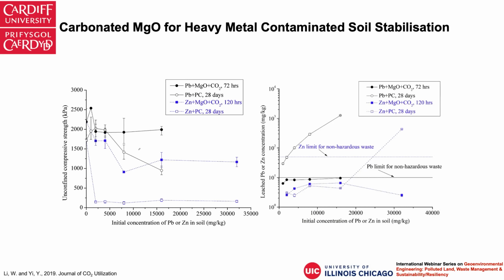So this figure shows that if you're looking at these solid points, you see that no matter how high the concentration of the heavy metals is, the carbonation system always develops much higher strength than the Portland cement system. And as I said, if you look at these points, you see that Portland cement hydration is indeed significantly hindered by high concentrations of zinc. But the carbonated magnesia system is much less affected.